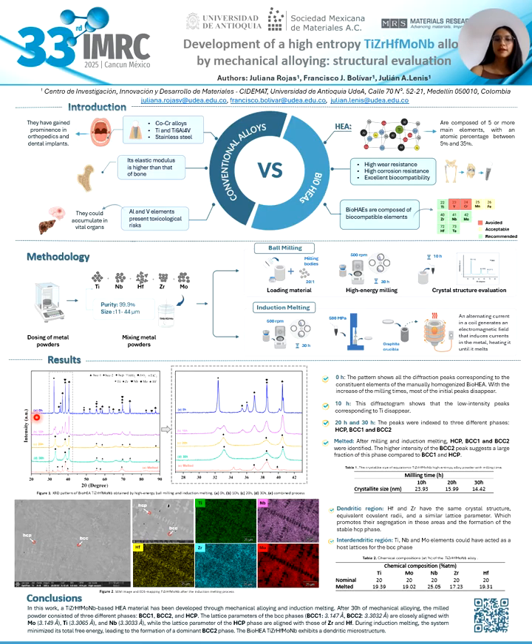These peaks are sharper and have a higher intensity than the intensity of powders subjected to longer milling times. With the increase of milling times, not only does the relative intensity decrease, but the diffraction peaks also become broader. This behavior is attributed to the intense impact energy during mechanical alloying that causes a reduction in the size of the crystal. The magnified view of the X-ray diffraction pattern between 28 and 42 shows that increasing the milling times, most of the initial peaks disappear.